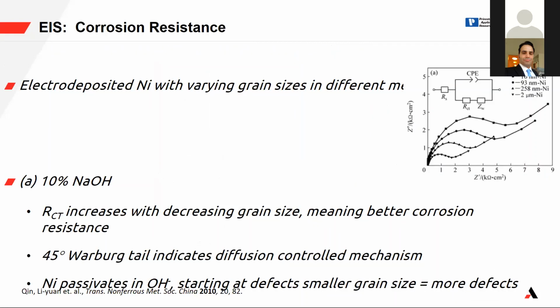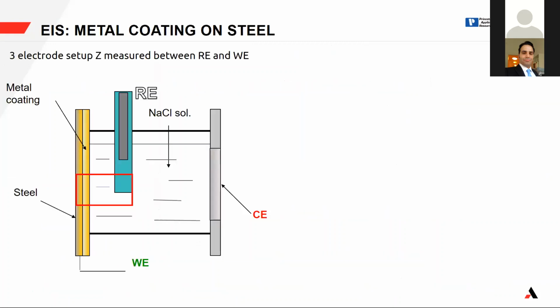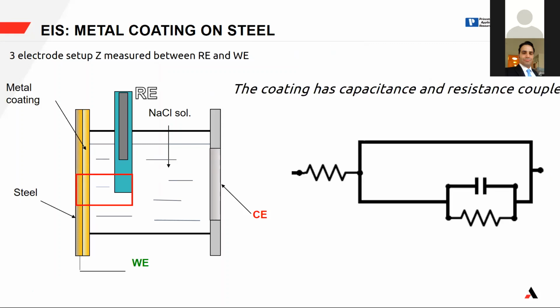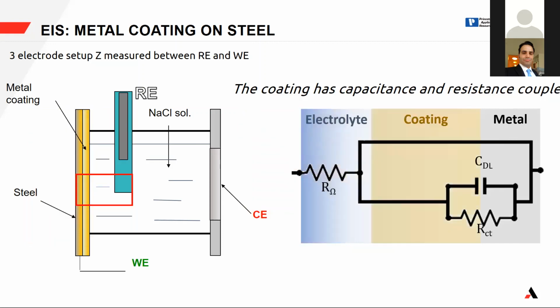It depends on the diffusion, your semicircle can change, it can explain, and you can have this. The last element that I want to show you is when I have some metal coatings or some conductive coatings. In this case, this is my setup, but then I have my metal, I have my electrolyte, and in between, I have the coatings. And the coatings I analyze as another resistance and double layer capacitor. So if I'm lucky, my coating is valuable enough to read, I can see, in this case, two semicircles, one for the coating and one for the metal.